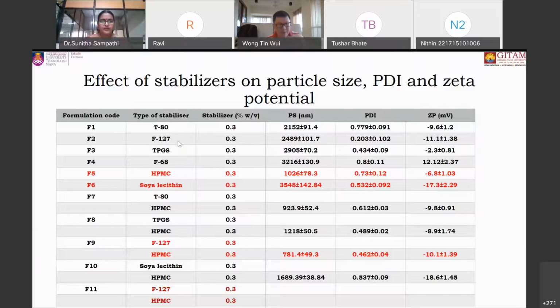If you see this particular slide, we initially selected a single stabilizer, and we used polymeric stabilizers as well as surfactant based stabilizers at a fixed concentration. Except for the polymeric stabilizer HPMC, in other cases we can see a larger particle size with a high PDI and the respective zeta potential. But if you look at HPMC, this is the one giving a particle size around 1000 nanometers. Even the soya lecithin is giving a very large particle size. So if these are the polymers and stabilizers which are available in the lab, we selected these.